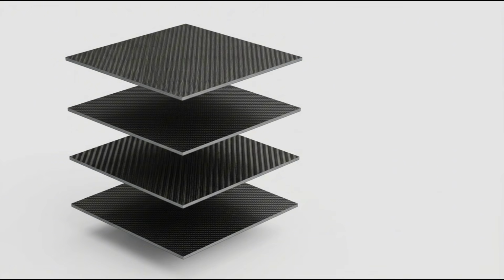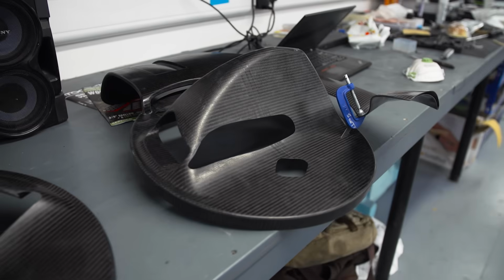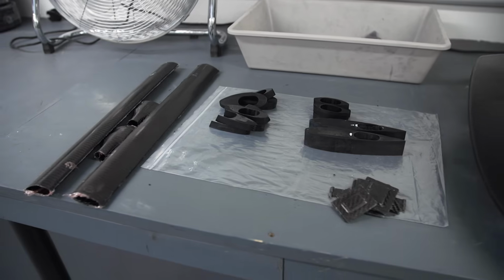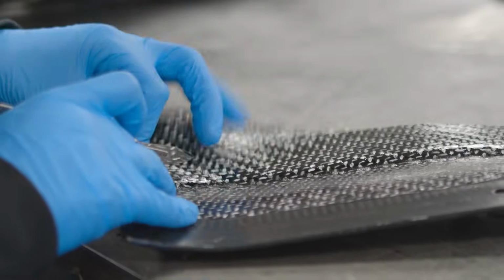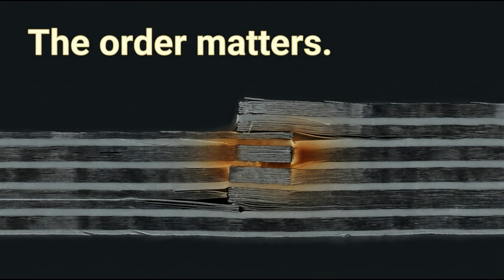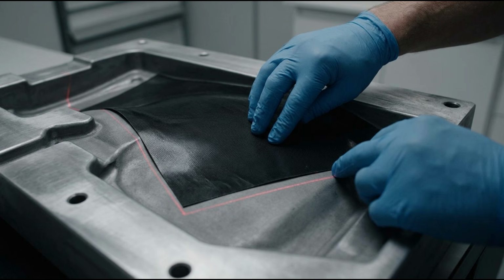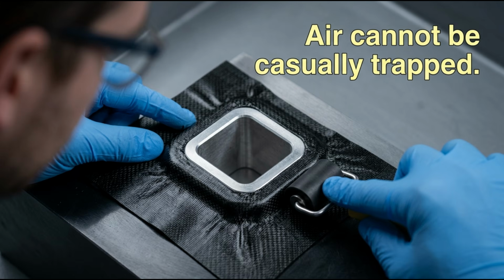If you bend a single unidirectional sheet across its weakest direction, it can feel surprisingly fragile. Align those fibers with the load, and the same material behaves completely differently. The order matters. The orientation matters. Even the position where one ply overlaps another can matter. Technicians lay the pieces into the mold according to a detailed laminate schedule. Laser projection systems may illuminate the exact boundary and orientation of each ply, but complex surfaces still depend on skilled hands. The material must follow tight curves without folding. It must sit correctly around inserts, corners, and transitions. Air cannot be casually trapped between the layers.